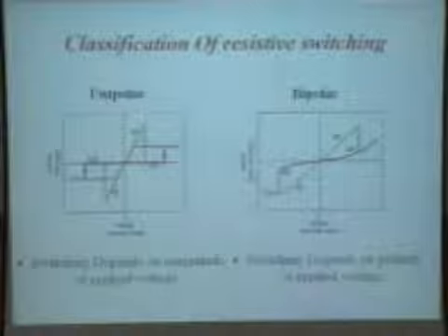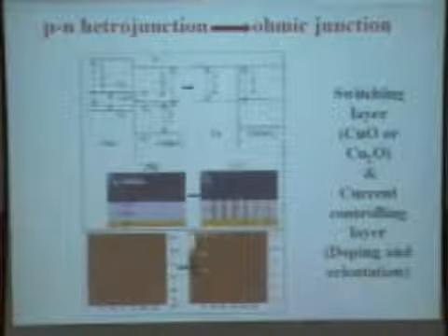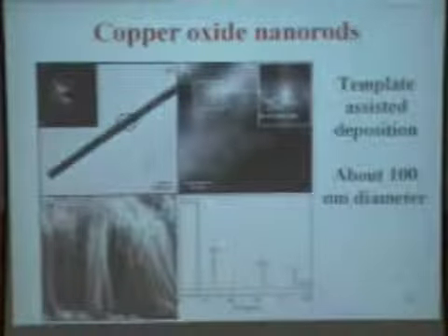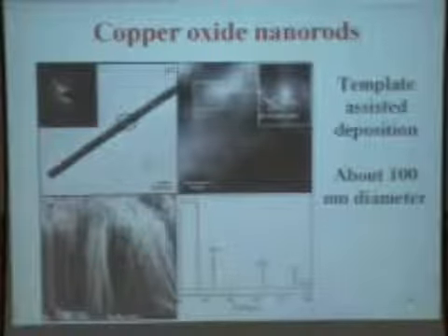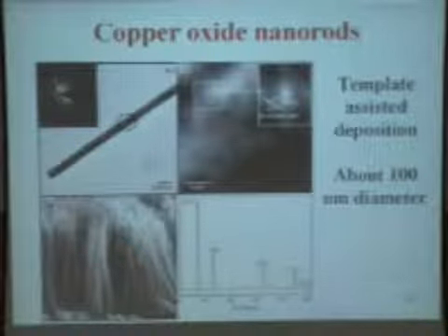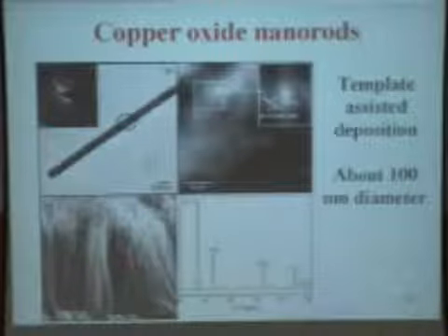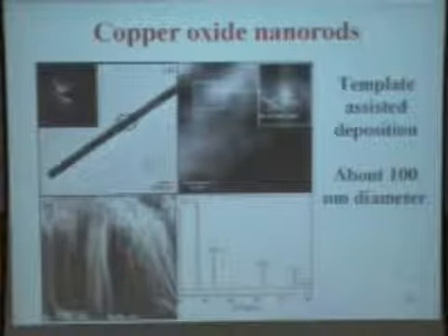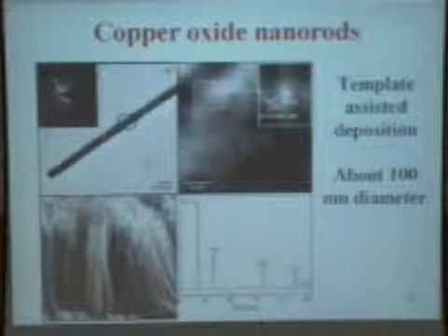One of the materials I will be describing is copper oxide, which has the filamentary mechanism. This is how the current-voltage characteristic looks, which I have already described. This is the structure; I think we can skip this. We were using a thin film, and in the thin film, as I already showed you, you form a filament, and the switching depends upon the formation of the filament.